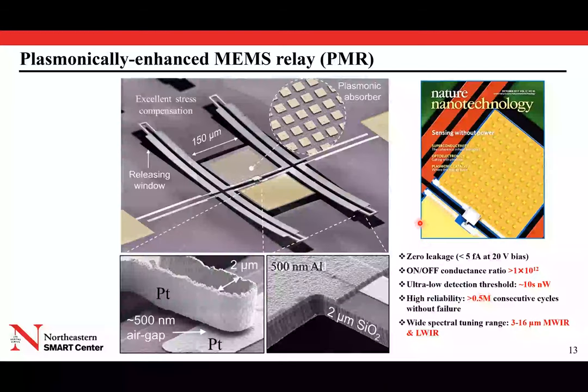So here is an SEM picture of one of the first devices that we fabricated. Let me highlight some of the important features that I described before. First of all, you can see that because of residual stress in the thin film materials, by the way, I didn't mention the materials, it's silicon oxide and aluminum, that's the bimorph cantilever structure. As you can see, there is some level of bending post-release of the structure. But as we discussed before, because of this sort of in situ compensation mechanism that we have in the structure, there is a near zero vertical displacement of the contact tip. So basically we can maintain a gap of 500 nanometers that was designed by process, with the sacrificial layer there. Another interesting thing I want to point out is this ball-shaped tip that I discussed before.